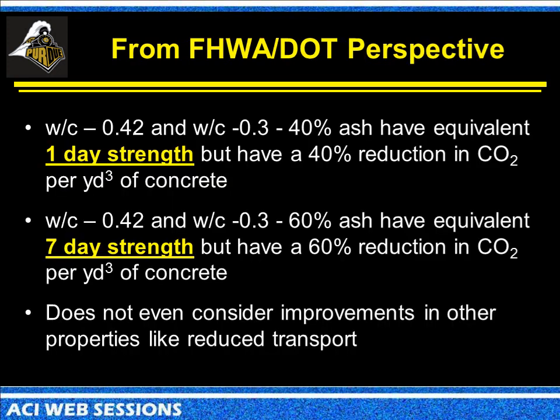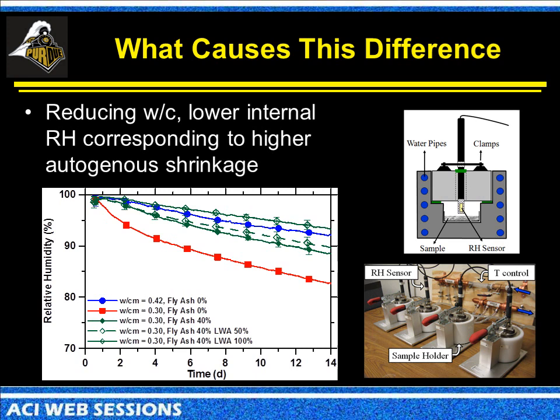So one of the things that we really wanted to focus in on is why do we see some of these benefits at early ages in reducing the autogenous shrinkage? So one of the things that we actually do to try to quantify this is we can measure the autogenous shrinkage that's taking place inside of the system. That's what I've shown you before. Here is a measure of the internal relative humidity that's inside of these systems. So we start the test right around 12 hours, and we measure the relative humidity as a function of time.